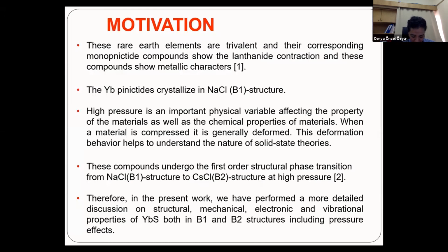These compounds undergo the first structural phase transition from the sodium chloride B1 structure to the cesium chloride B2 structure at high pressure. Therefore, in the present work, we have performed a more detailed discussion on structural, mechanical, electronic, and vibrational properties of ytterbium sulfide in both B1 and B2 structures, including pressure effects.